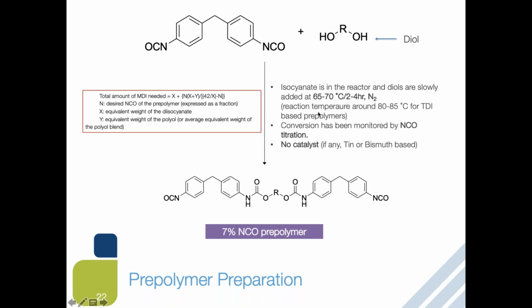For our study, most isocyanates require very mild conditions, a temperature around 65 to 70 degrees C for a few hours with a nitrogen purge. However, if you're dealing with TDI, an isocyanate that has low reactivity, you can use a higher temperature to achieve proper synthesis. Your conversion can be monitored using isocyanate titration, and to accelerate the reaction, you can choose a proper catalyst. In our study, we did not use any catalyst, but if you want, you can use a tin or bismuth type of catalyst to accelerate your reaction.